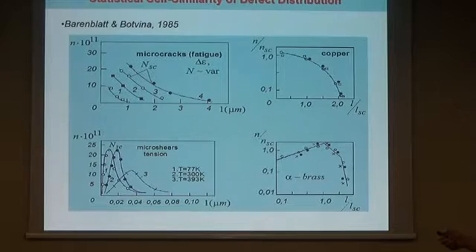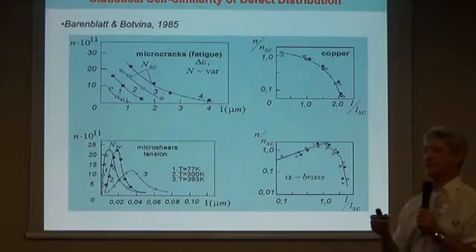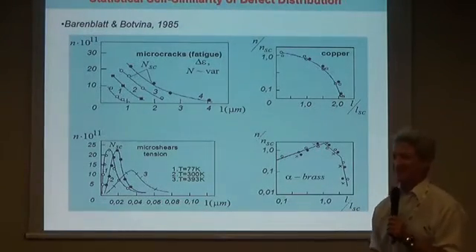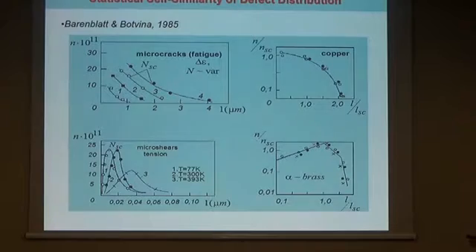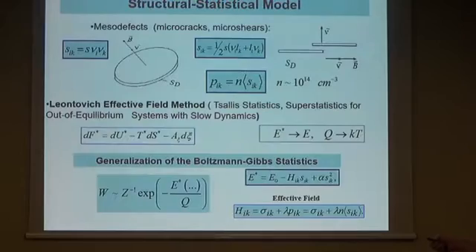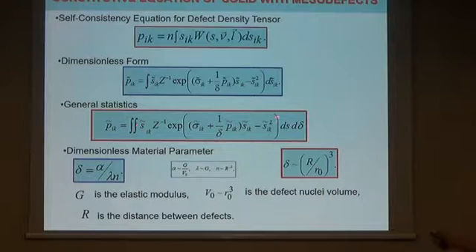It was very stimulating for us, along with experimental data concerning statistical self-similarity obtained by Professor Barenblatt and Professor Botvina. That was very helpful to develop statistics when we introduced typical defects, and it was due to a generalization of Boltzmann-type statistics. A procedure of averaging was realized that allowed us to obtain a constitutive model in the variables of defect density and some other structural variables that represent the ratio of characteristic size of defects and spacing between defects.